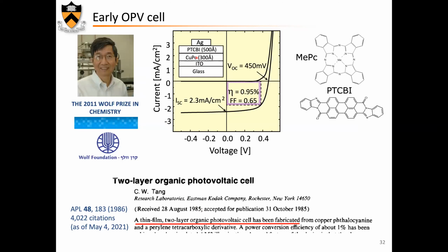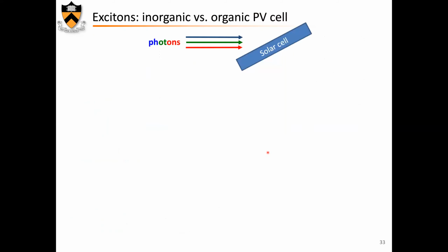So this was a rather simple cell, as you will see from the evolution, with two materials, this copper phthalocyanine and this PTCBI, these two molecules, and I will explain why. As you can see, the efficiency of the device was just slightly below 1%, so at the time, not great, but it has evolved considerably since, as you probably know.